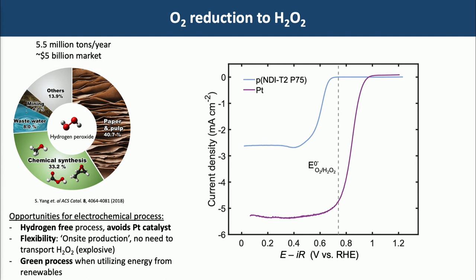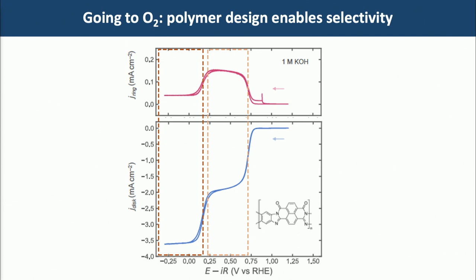I'm showing there the platinum catalyst because, well, it looks like it performs a lot better. It does. But it's performing a different reaction. That one is reducing oxygen to water. So our catalyst actually stops at hydrogen peroxide, so it's also chemically selective. It produces the chemical that we wanted to produce. And now remember, you can design polymers to do different things, and so it turns out there is another polymer that can go all the way to water as well.